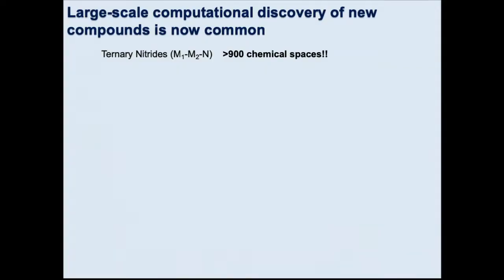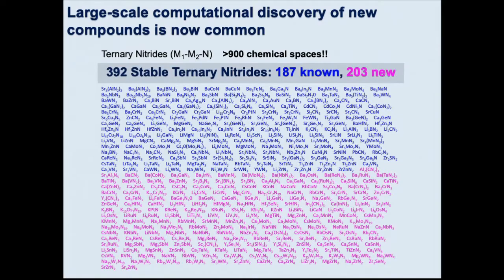And so I'm just going to give you the short of it. We studied 900 chemical spaces, right? One chemical space is one choice of this doublet here. And so we found 392 stable ternary nitrides, of which about 200 were known and about 200 were new. So in some sense, overnight here, we've doubled the number of known ternary nitride compounds.